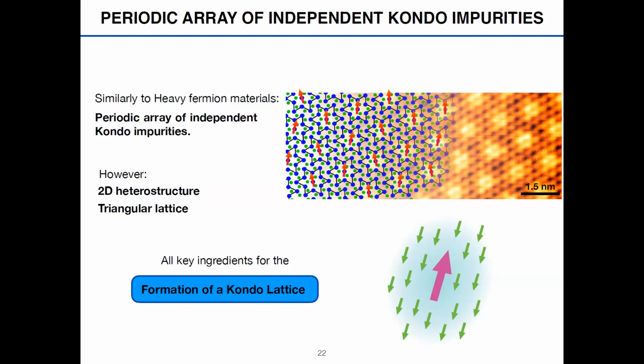So what you have basically on the surface of the 1T is a periodic array of independent Kondo impurities, okay? And this is similar to what you have in a heavy fermion 3D metal, you know? This lattice of magnetic impurities embedded in a metal. However, there's some difference. It's a 2D heterostructure, and because the periodicity of this array of Kondo impurities is the one of the 1T charge density wave, it's a triangular lattice.